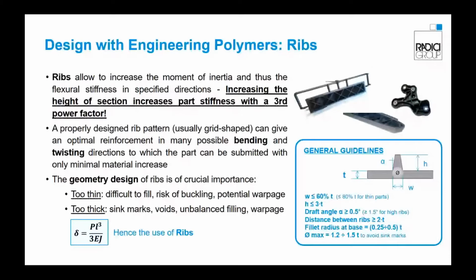Geometry of the ribs has a crucial importance. Thin ribs are difficult to fill, and the risk of buckling and potential warpage are present. At the same time, thick ribs lead to sink marks, voids, and unbalanced filling. Hence, use the ribs following the general guidelines reported in the right picture in order to ensure the right part stiffness along with a good injection molding process of the parts.